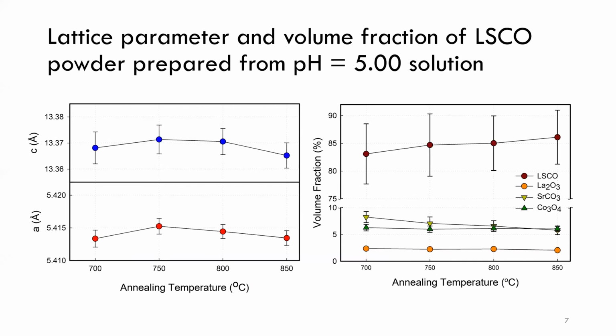Rietveld refinement method was used to calculate the lattice parameter and the volume fraction of the LSCO powder prepared from pH equals 5 solution. Calculated lattice parameters show that there is no significant change in the unit cell size for all heat treatment temperatures used in this study. The calculated volume fraction shows that most of the samples prepared are LSCO dominant phase. Moreover, there's a slight increase in the volume fraction of the LSCO as we increase the annealing temperature, while a slight decrease in the strontium carbonate phase. It can be said that the increase in heating temperature possibly decomposes the strontium carbonate phase, which then reacts with the other metal oxides to form LSCO.